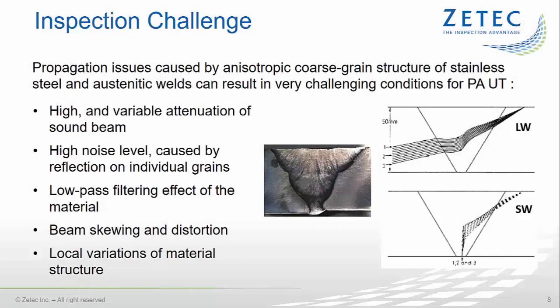After this introduction, let us now dive into the specific challenges presented by austenitic steel welds when performing ultrasonic examinations. As opposed to regular carbon steel, these materials are anisotropic, which means that the physical characteristics of the material depend on the orientation of the crystal. In practice, for UT examinations, this means that the wave velocity and the attenuation will depend on the relative angle between the acoustic beam and the crystal.